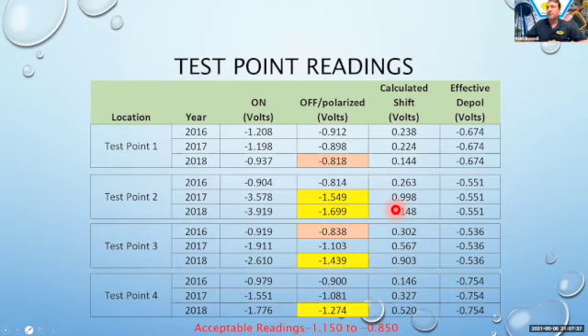So there's a concern here with some of the data that Alyeska has been collecting, that they've got some elevated polarized potentials like this, and they recognized it in notes that they've made, because of the proximity of that linear anode, that they're probably being influenced by that linear anode even when it turns off. So they acknowledge it, but that's the extent to which they carried it out, at least at that time. The concern here is, if we have an error in this set of readings, do we carry that same kind of error in this reading over here? So there's some concern with the quality of that data.